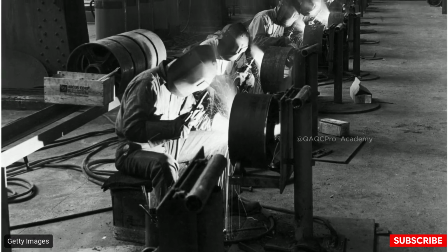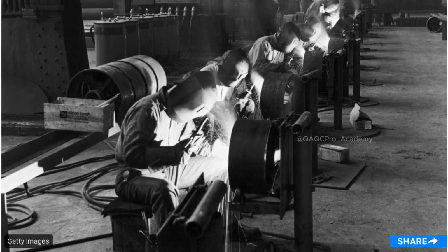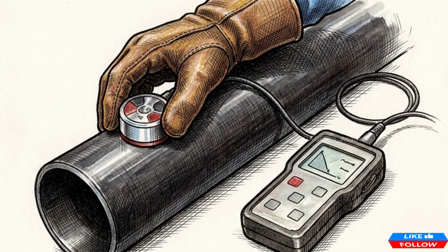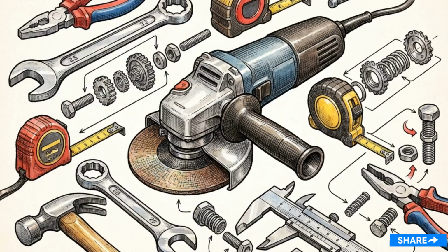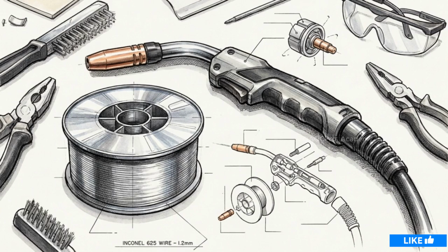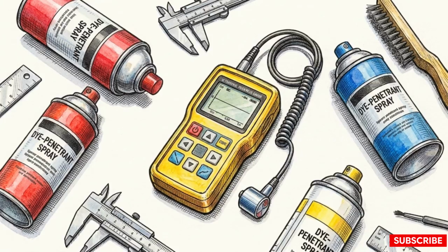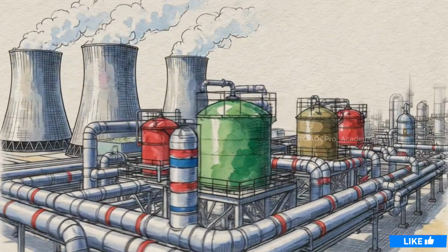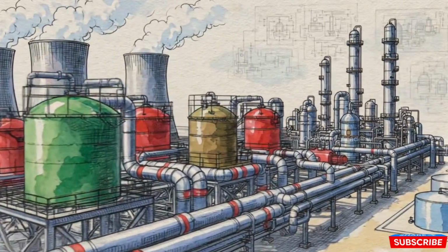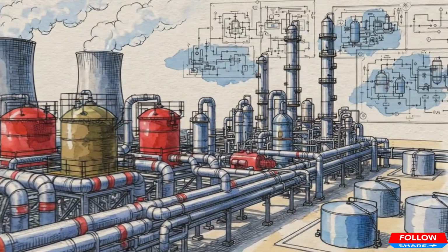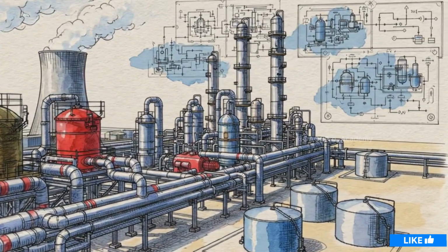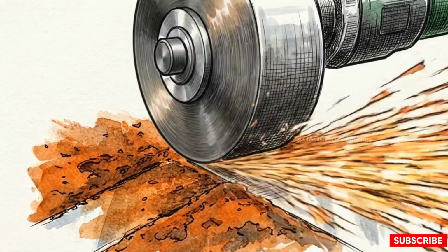True mastery of this process requires more than just applying the metal. You must be able to prove the integrity of the bond without ever making a destructive cut into the pipe. This workflow requires an angle grinder for surface prep, a MIG welder with Inconel 625 wire for the overlay, and a specialized non-destructive testing kit, including an ultrasonic gauge and dye penetrant. Getting this cladding right prevents environmental disasters, extends the operational life of the hardware, and removes the need for frequent, expensive repairs. Preparation is the most critical phase.